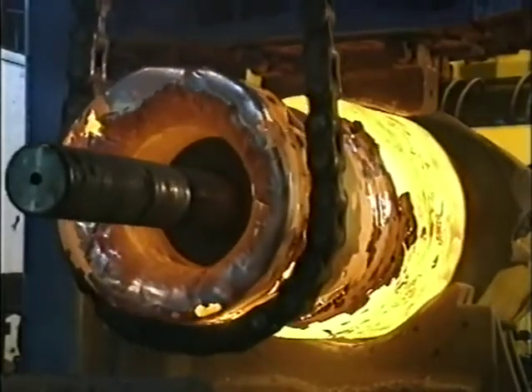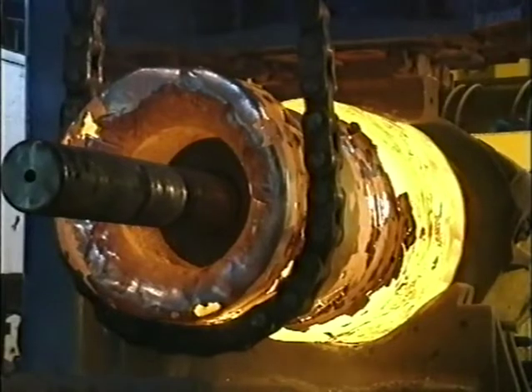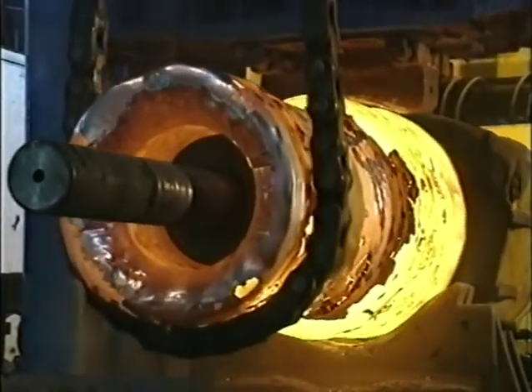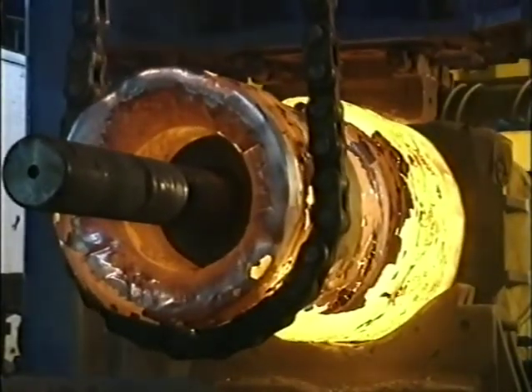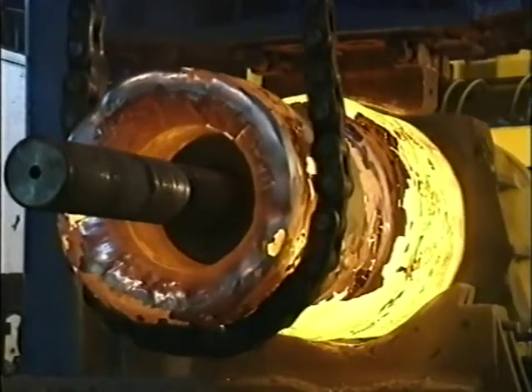The intense pressure and high temperature cause the metal crystals to first elongate and then recrystallize to a smaller grain size as forging progresses. These grains are squashed and elongated in the direction of working. This can be controlled by careful attention to the chemical composition of the steel, the temperature, and the extent of squeezing. A smaller grain size promotes a stronger, tougher finished product.